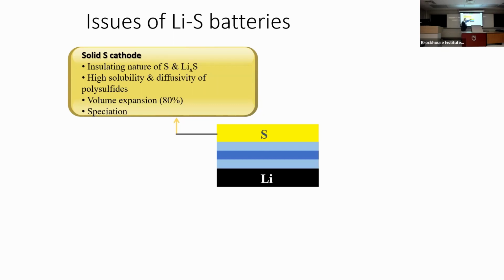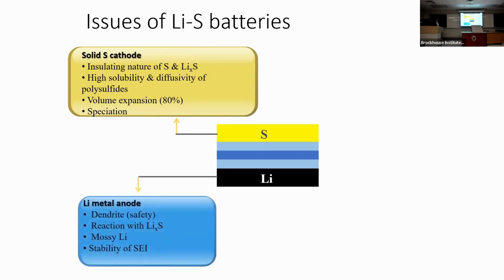The polysulfide that forms here will diffuse. Some of it will dissolve, some of it will react with lithium chemically. So that kind of energy is lost. So there's a tremendous amount of loss of energy, capacity fade that takes place. Okay. And there's a volume expansion that takes place on this side when sulfur becomes Li2S. And therefore, you find that this material begins to break down as well. So for reversing the reaction, it becomes harder.